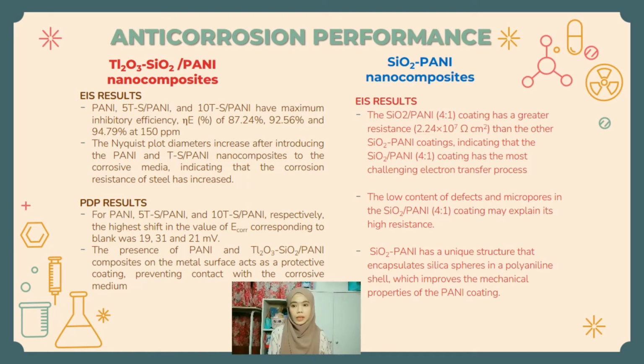For the PDP result, the highest shift in the value of E-corr corresponding to the blank was 19, 31 and 21 mV. The presence of polyaniline and titanium trioxide silica polyaniline composite on the metal surface acts as a protective coating, preventing contact with the corrosive media. The EIS result for the silicon dioxide polyaniline coating with the weight ratio of 4:1 shows greater resistance than the other silicon dioxide polyaniline coatings, indicating that the 4:1 coating has the most challenging electron transfer process.